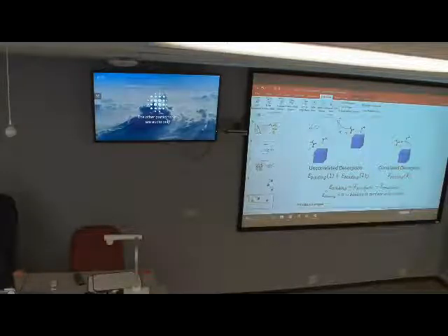You can compare the binding energies to see which process will be more favorable for desorption. And just for notation, I took binding energy as the energy of all the product states minus the energy of all the reactants. That way, if our binding energy is positive, that would indicate that the ligand staying on the surface will be more favorable than coming off the surface.